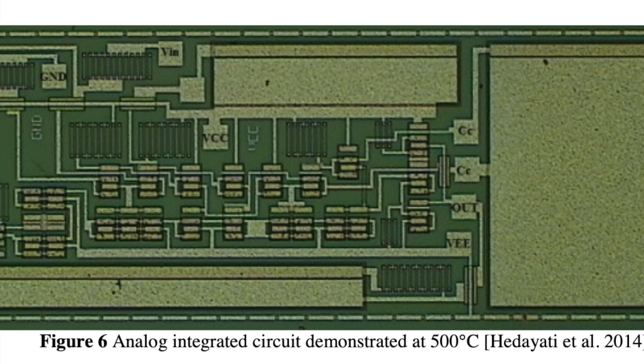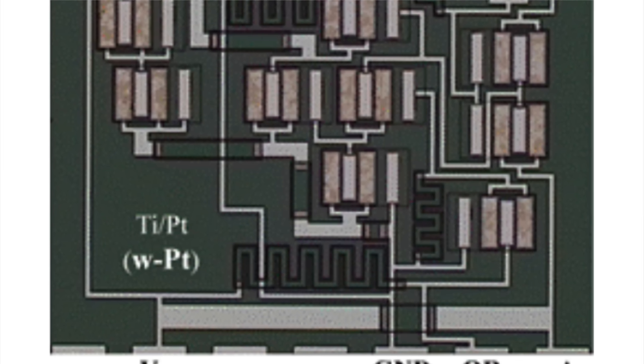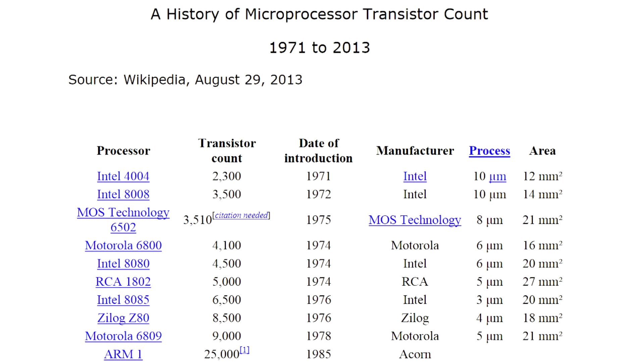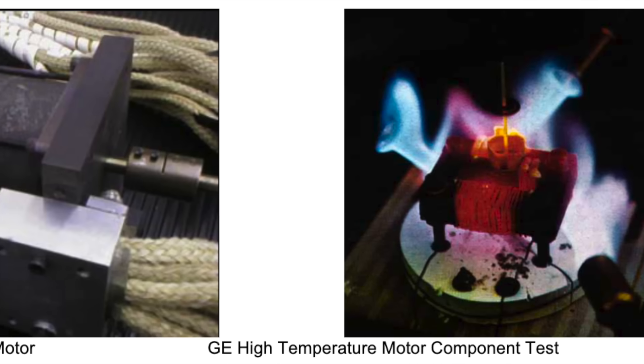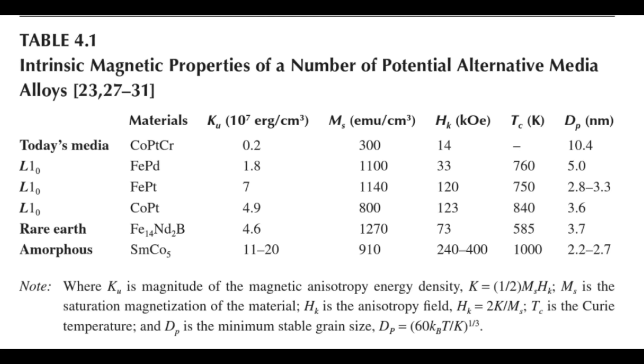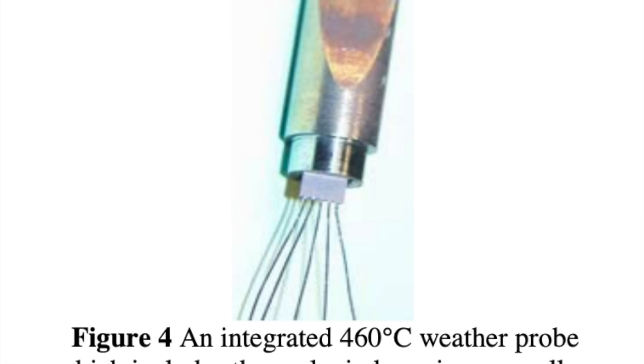If you put these silicon carbide electronics in there, they were able to run for 22 days nonstop at Venus temperatures, which is surely a good sign. But these chips are very simple — about 100 transistors. That's a long way to go to build a working microprocessor. The simplest microprocessor is probably the Intel 4004, which had 2,300 transistors, whereas today's processors have billions. You could go with a basic 8-bit processor with less than 10,000 transistors. On top of this you're going to need transistors for memory — dynamic RAM uses a capacitor and a transistor for every bit, so you need as many transistors as you have bits of memory. For non-volatile storage, you can't use off-the-shelf hard disks either, as many magnetic materials lose their magnetic properties at these temperatures. So you've got to come up with something custom to store this data.